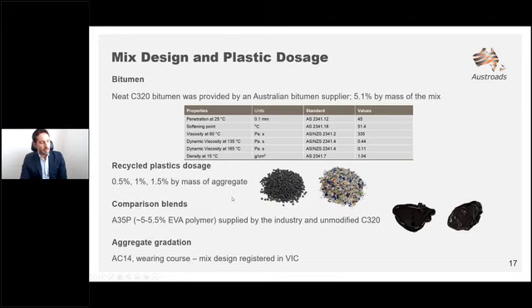experimentation. We also compared the mix design at 0.5, 1, and 1.5% plastics with standard conventional polymer modified binders, specifically an A35P, which again, if you are outside from Australia, is a combination of 5 to 5.5% EVA polymer. And we compared the results also with unmodified C320.